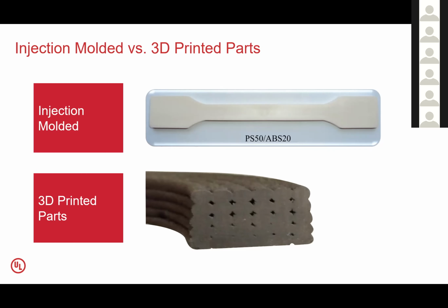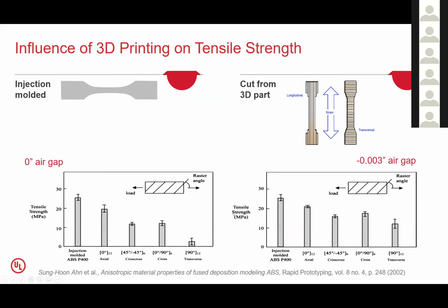And this can be seen very clearly in the mechanical studies that were done almost 20 years ago, where they looked at an injection molded ABS material and they observed a certain tensile strength. Then they took that material and 3D printed it longitudinally in the direction of our tensile bars and measured a different tensile strength, a lower tensile strength. When they took that material and printed it in the cross direction of our strain, they got yet a different tensile strength. And in this case, you can see that there's almost an order of magnitude difference from that same material, depending on how it's being printed.